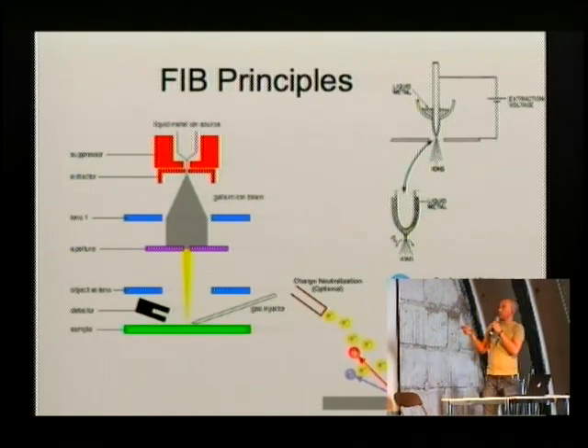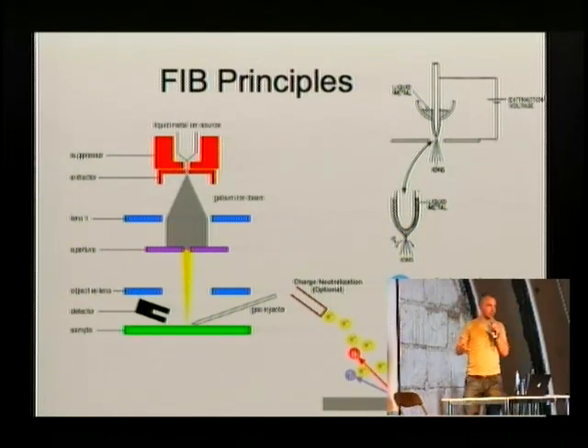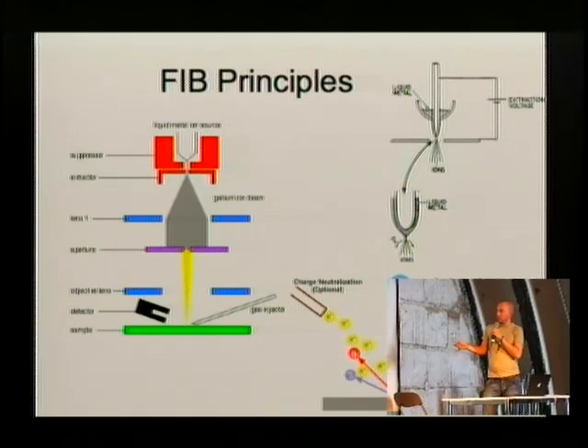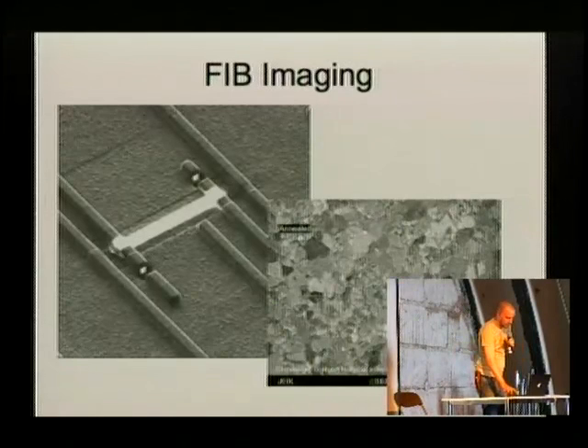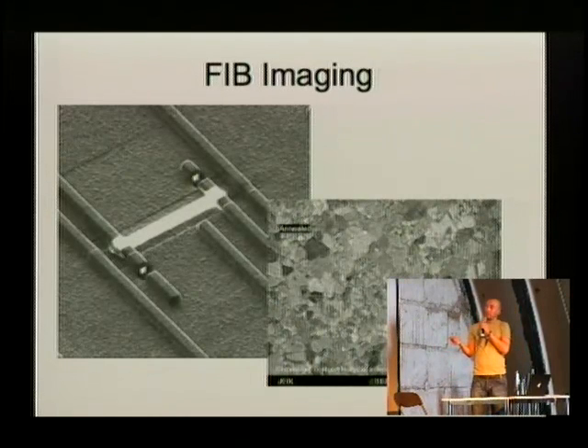Once you have these gallium ions coming out of this tip, you can do the same as you did in the electron microscope. You send them through a lens system. You have again some sort of deflection mechanism that scans your beam over the sample. And the beam, in a similar way to the electrons, creates secondary electrons that come flying out, and you can detect those. So you can use the FIB, the focused ion beam, for imaging.